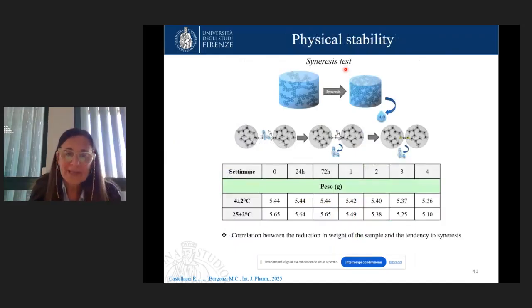During the physical stability test, we characterize the gel from a rheological point of view. We check at different times the rheological behavior of the gel and also the water loss during the storage. We store the gel containing micelles with usnic acid at 4 or 25 degrees centigrade, and at different weeks we weigh the gel to evidence the water loss. We observed from the results that the gel is stable, and we have also a little water loss at 25 degrees centigrade after 1 month.